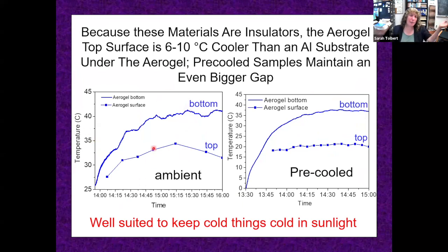This is when we just take a sample at room temperature and put it in our little setup and measure the temperature. This one is interesting because here we put a sample in the refrigerator, cool it down, and then we take it out and put it in our setup. And we find that the top does not heat up at all. So we got it cool and it stays cool because it sends any incoming heat out to the vacuum of space. So this kind of material is really well suited to keep things cold in the sunlight.